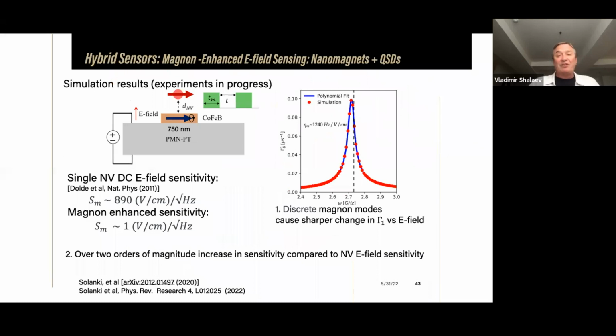Of course, you could invert this problem and say, hey, the electrical field controls this relaxation time, but what if, by measuring this relaxation time, I could define what is the electrical field which caused it? But for that, you would like to have a sharper resonance. For example, you could pattern your magnetic film that supports magnons, collective spin excitations, so that the resonance would be sharp, like it's shown here. And we showed that in this case, you could use this magnon-enhanced sensor to detect electrical field with record high sensitivity, which is 2 orders of magnitude higher than the one used with conventional NV centers. So that's kind of the approach which will involve magnons, local spins, microwave photons, and optical photons for more complex quantum systems, which could be used as quantum repeaters, quantum sensors, and so on and so forth.